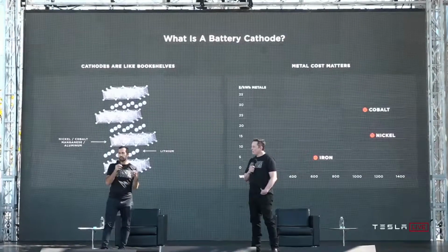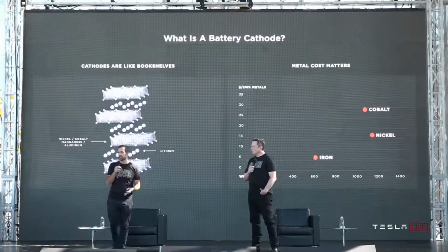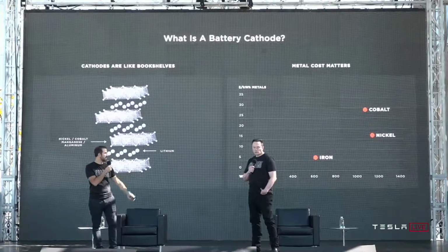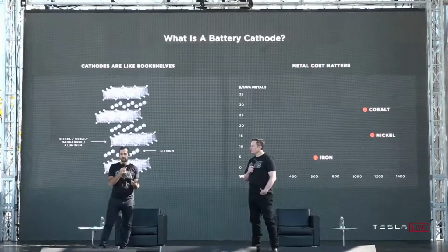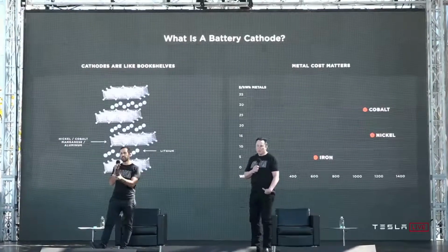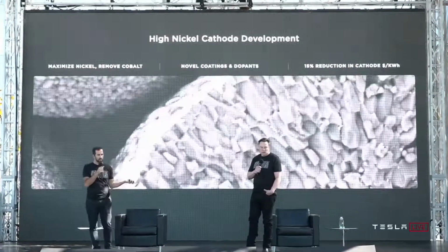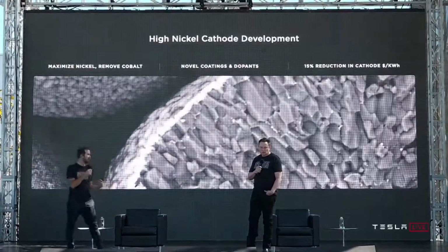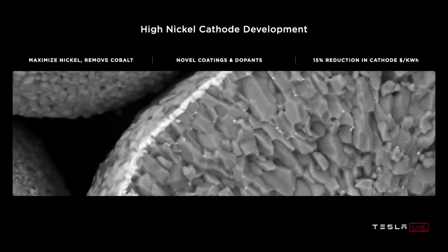But one of the reasons why cobalt is even used at all is because it is a very stable bookshelf. And the challenge with going to pure nickel is stabilizing that bookshelf with only nickel. And that's what we've been working on with our high nickel cathode development, which has 0 cobalt in it. Leveraging novel coatings and dopants, we can get a 15% reduction in cathode dollar per kilowatt hour. Yeah. It's a big deal.